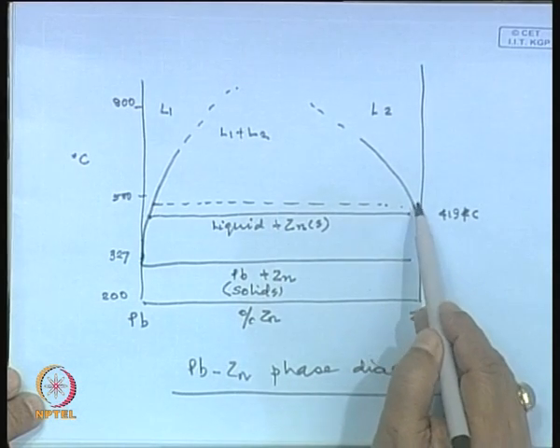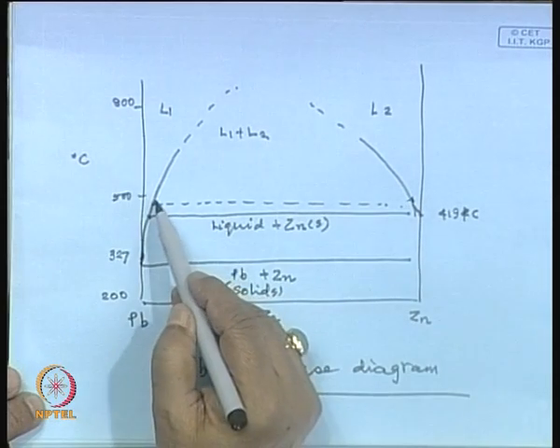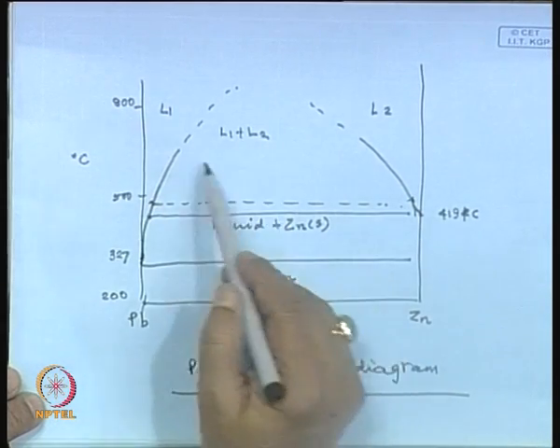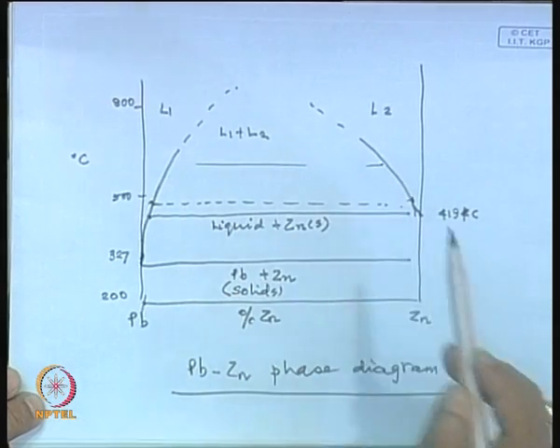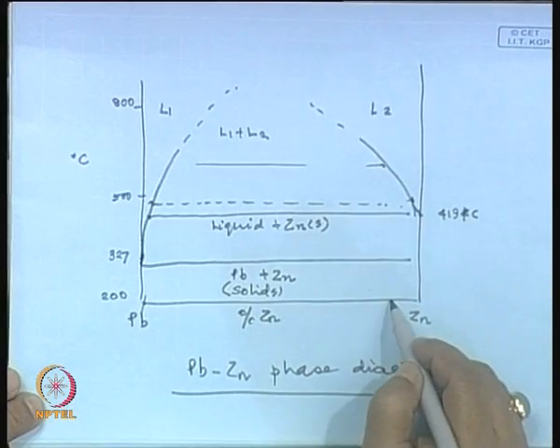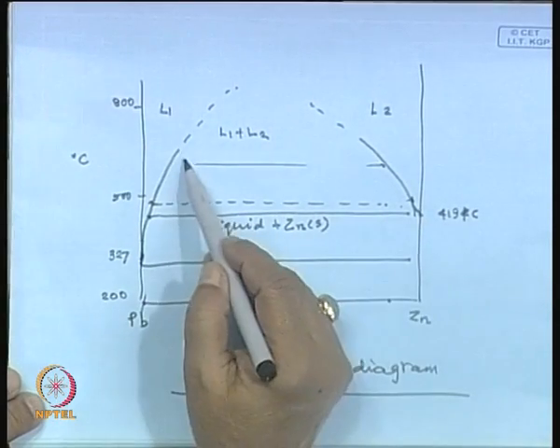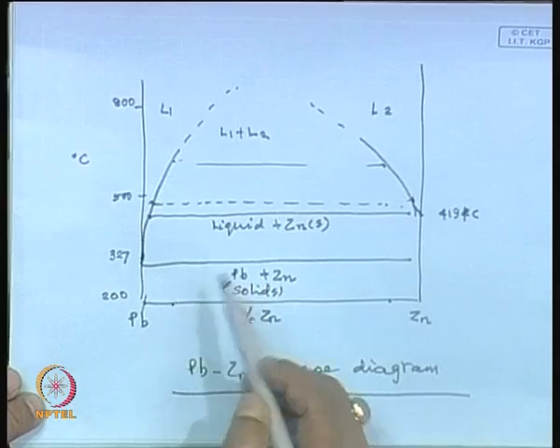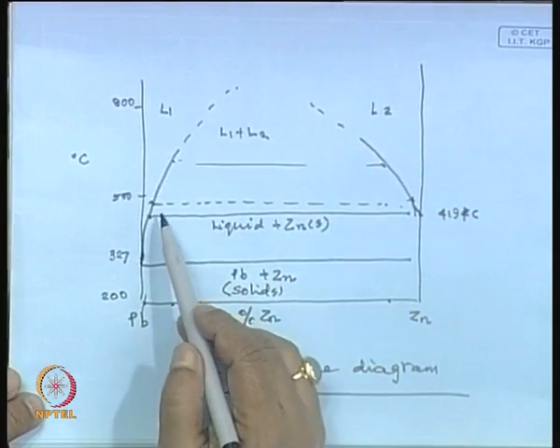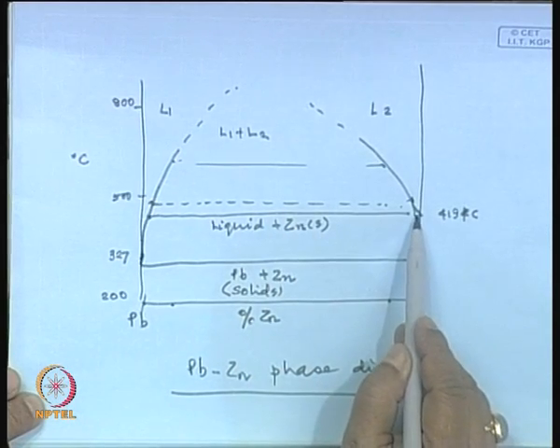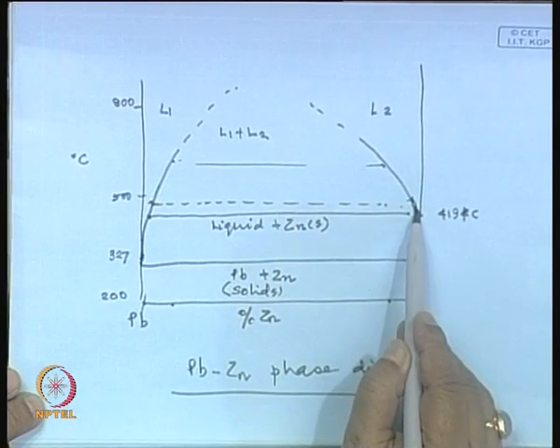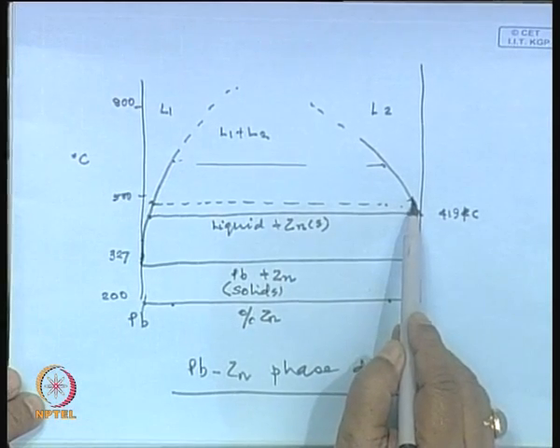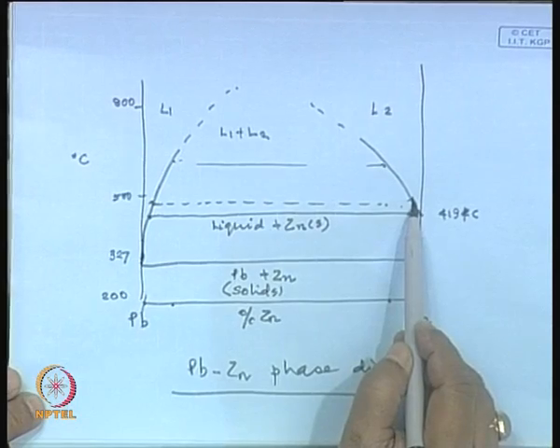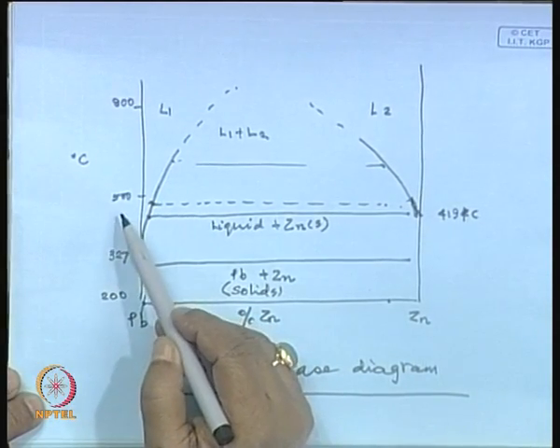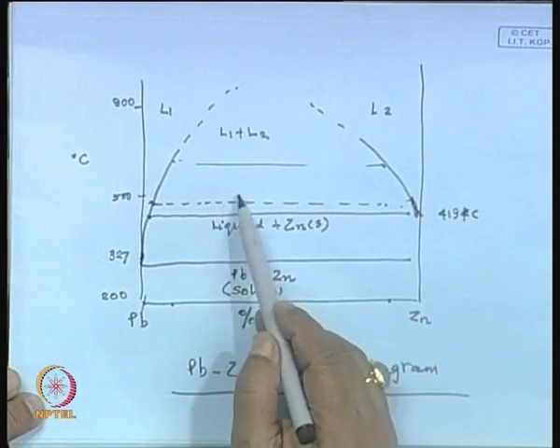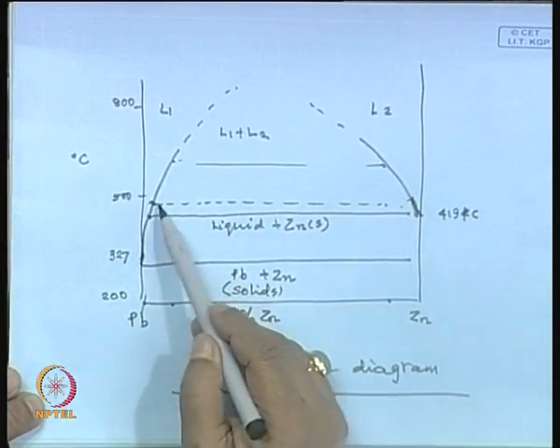One liquid is very rich in zinc, the other liquid is very rich in lead. If we go to a temperature like this, we will have a liquid which is richer in zinc, and a liquid richer in lead, and this actually comes down. But if we are somewhere here just above the melting point of zinc, there is very little zinc, very little lead in what is separated out, and there is some amount of zinc which is in the other liquid. So, here we get two liquids, this liquid and that liquid. Okay.